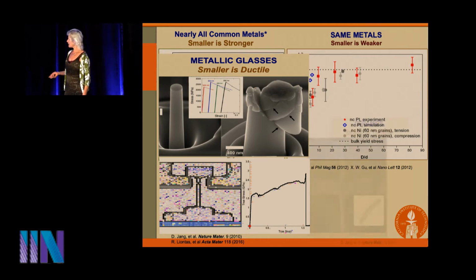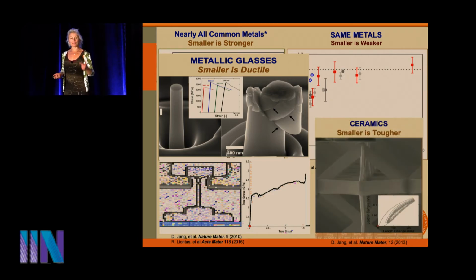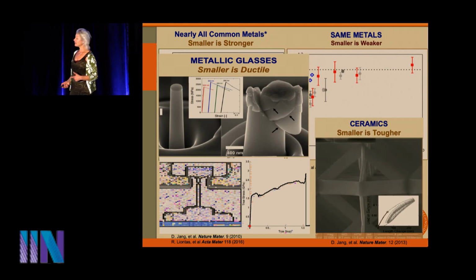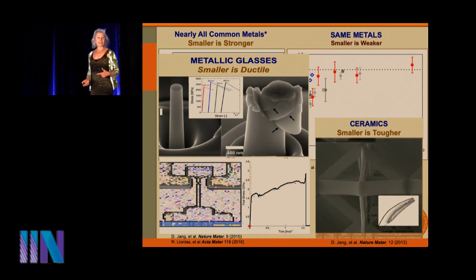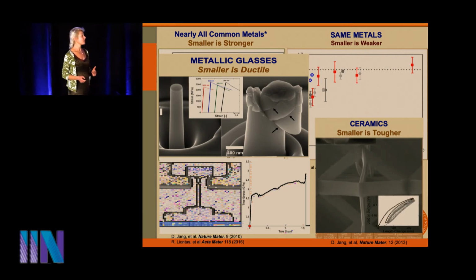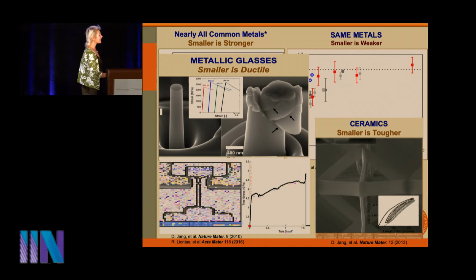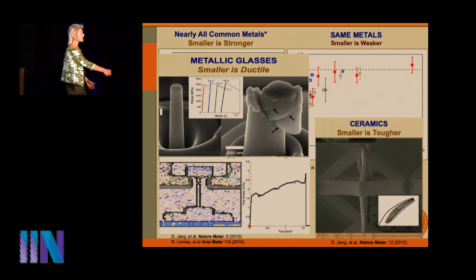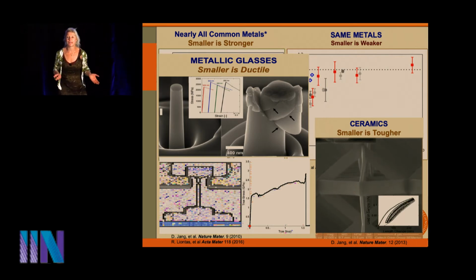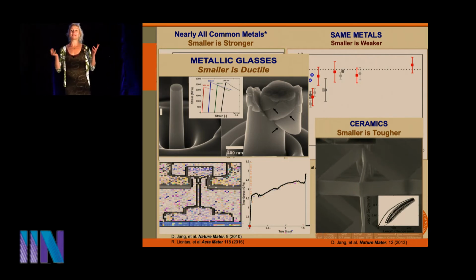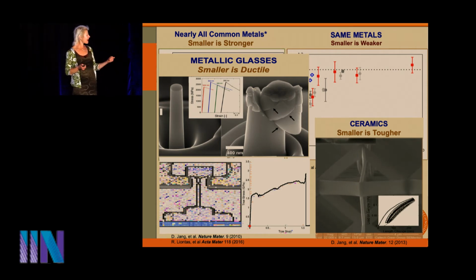Here's the last example. If you look at a ceramic nano architecture, this is just a single unit cell. So this is made out of titanium nitride, very, very brittle ceramic, and we're pushing on just a single unit cell. What you see is that these beams are deflecting, and they're deflecting so much so that the tensile stresses that are generated here exceed 1.5, 1.7 GPa. No ceramic should stay intact at 1.7 GPa of tensile stress. But this guy, not only is he staying intact, but he's doing this over multiple cycles.